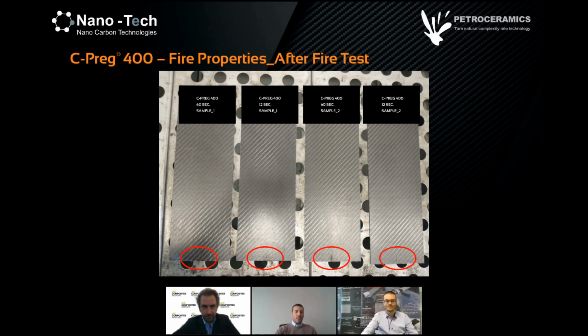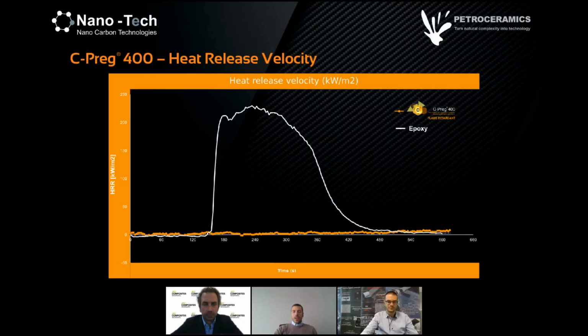Okay, here we have a picture of the specimen after the testing. As you can see, there is just a little sign of smoke on the specimen. We tried to do 2 different thicknesses. And I don't think with other organic material you can achieve those properties. Then we will show a chart done by the calorimeter test. This is the chart of heat release of the specimen. And you can see we tested a normal flame retardant epoxy against our Cpreg. As you can see, there is no ignition time.